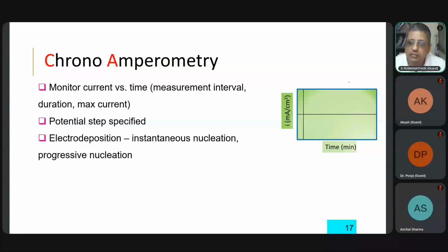This is useful when you're looking at electrode deposition. When you deposit, for example, copper, or you're using a rechargeable metal air battery, you're electrically depositing zinc from the solution. Depending on how that is done, whether the deposition happens by progressive nucleation of these seeds, or is it happening at an instant nucleation? Deposition will happen continuously, but nucleation, is it happening very quickly?